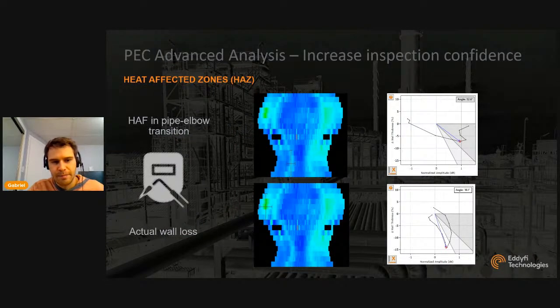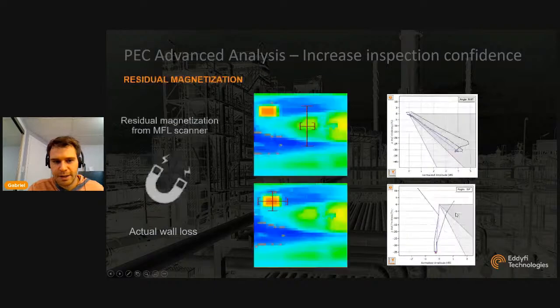Here we've got, this is basically an elbow where we scanned also 30 centimeters, 1 foot on either end of the elbow on the straight sections. We've got the heat affected zone from the weld here. So this one is affecting this kind of hourglass shape, is affecting the PEC sizing, but the PERM tool confirms that this is indeed a false positive. Where we put the cursor on this generalized corrosion defect here, just on the left, we see that this is indeed identified as a real indication.